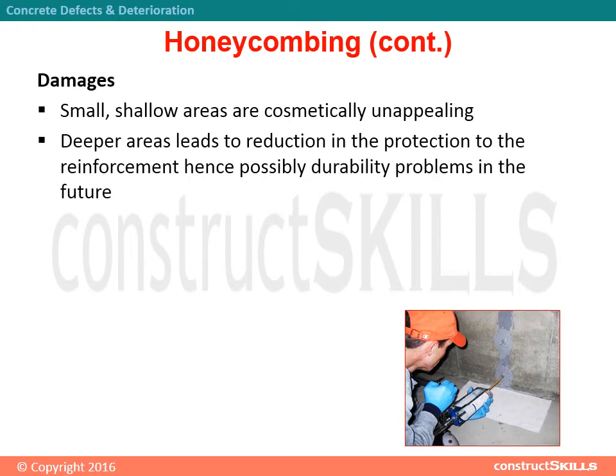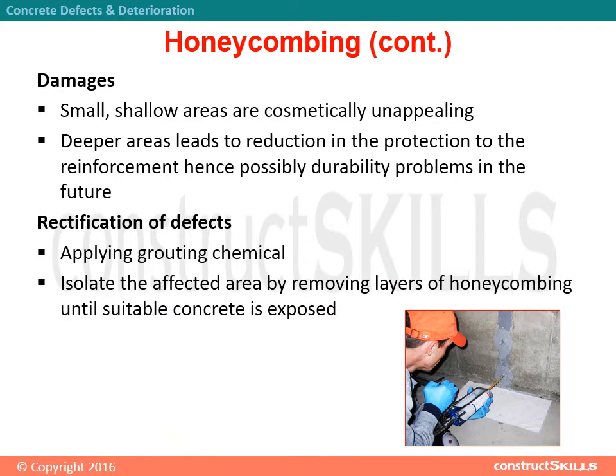Damages from honeycombing: small, shallow areas are cosmetically unappealing, while deep areas lead to a reduction in protection to the reinforcement, potentially causing durability problems in the future. Rectification involves applying grouting chemical and isolating the affected area by removing layers of honeycombing until suitable concrete is exposed.